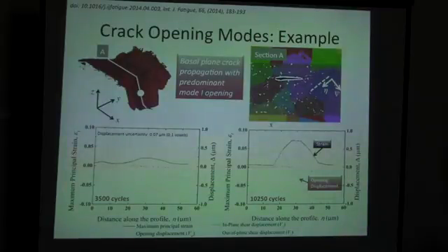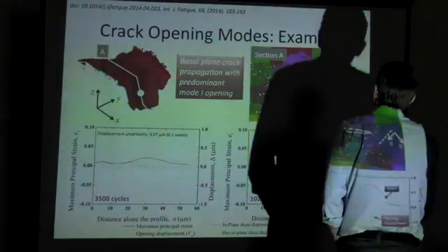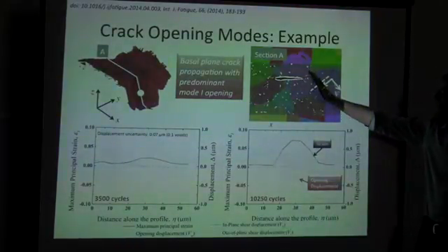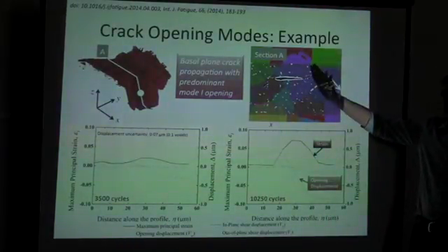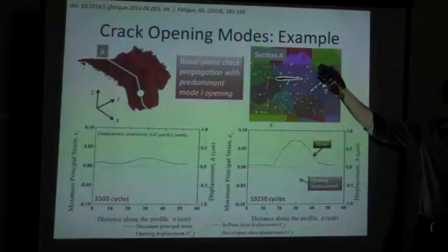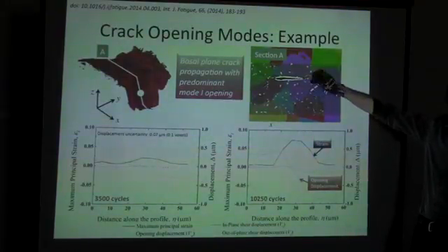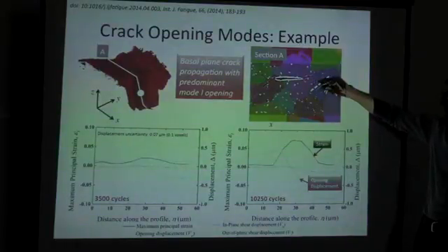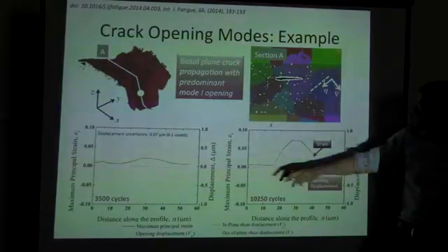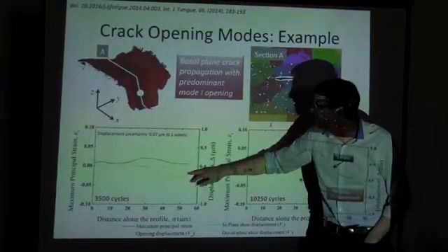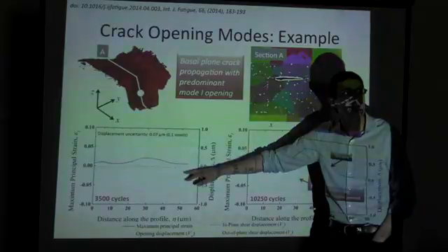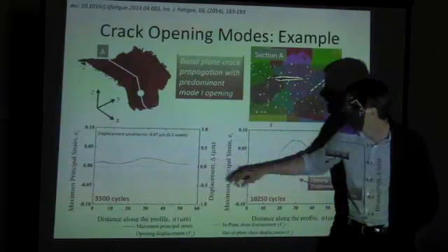And maybe the last slide: because you can measure the displacement field in 3D, we can take the crack that we're interested in. We know the three-dimensional orientation of the crack. We have the full displacement field. We can measure the displacements perpendicular to the crack plane and in the crack plane and say, well, is it mode 1 opening? Is there any shear going on? This is the measurements that you take before the crack's gone through that bit of region. That's basically the noise, the measured uncertainty.